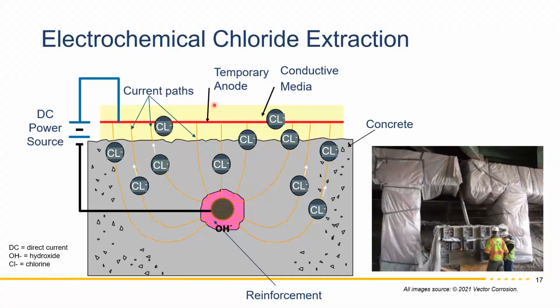You put a temporary anode, basically a conductive mesh, and the chloride is driven back out, so you reverse the process back into this conductive medium. It takes about a month or two. This is a process that was done on I-95. Of course, the traffic was not stopped, so the columns were basically cleared of the chloride, and they did some patching. And then once that was done, they replaced the superstructure.